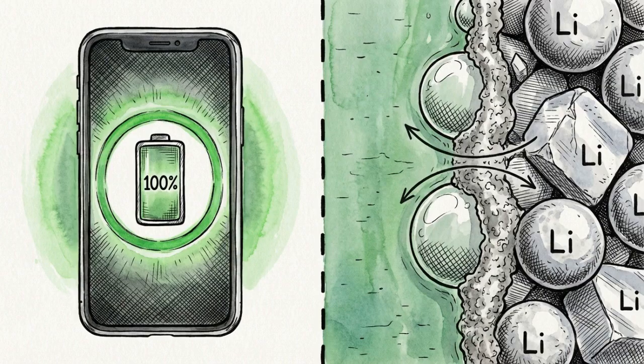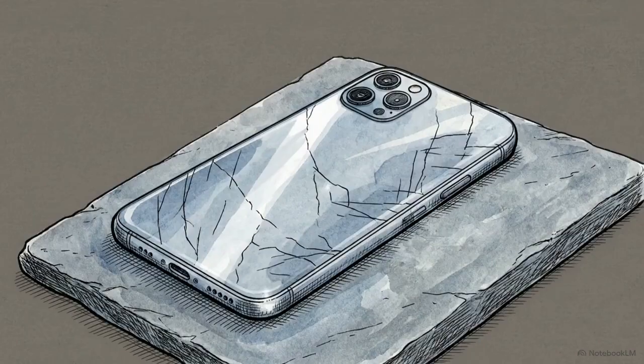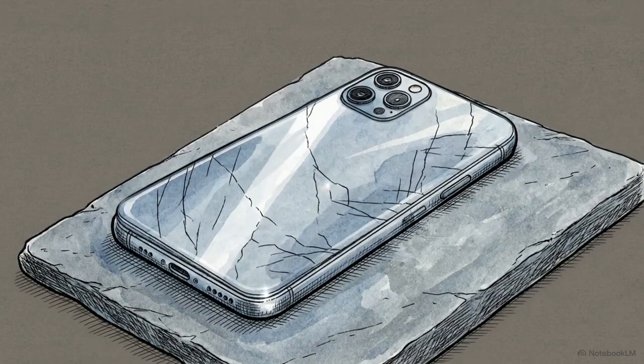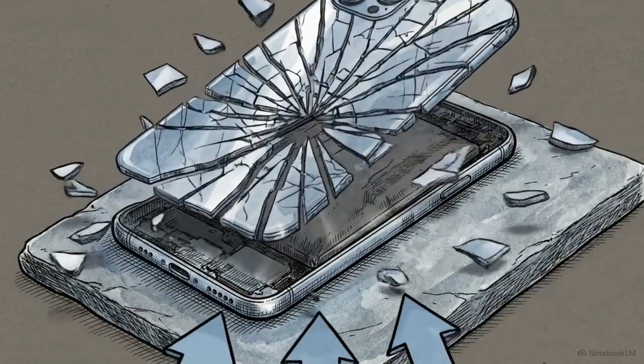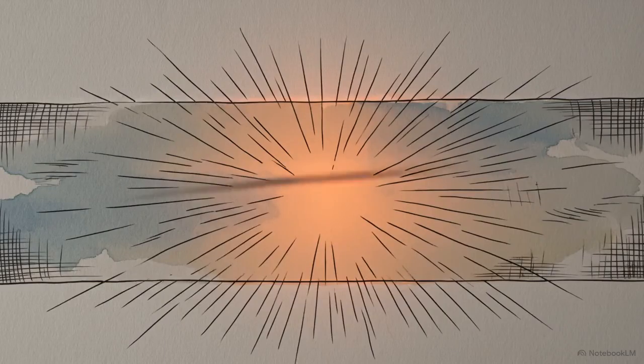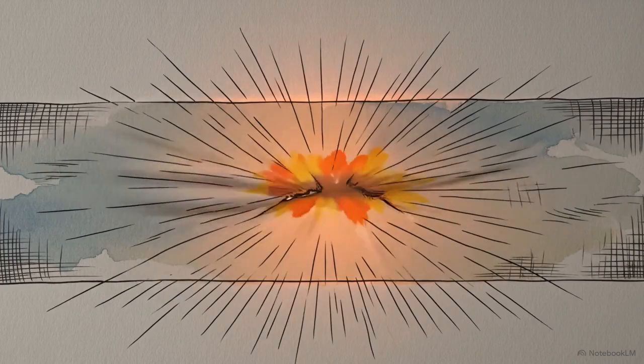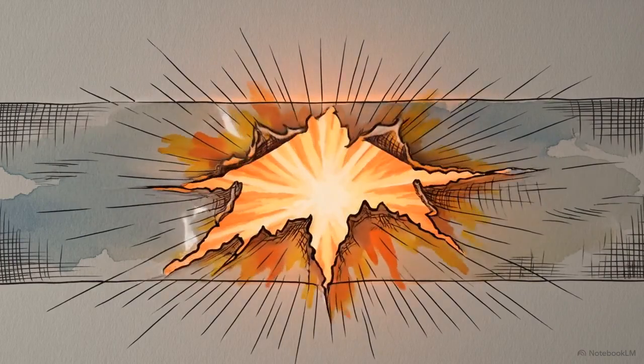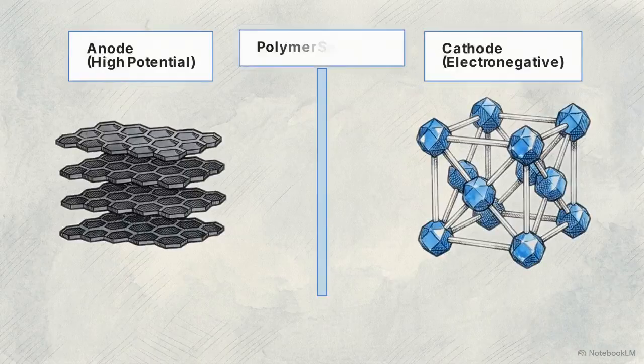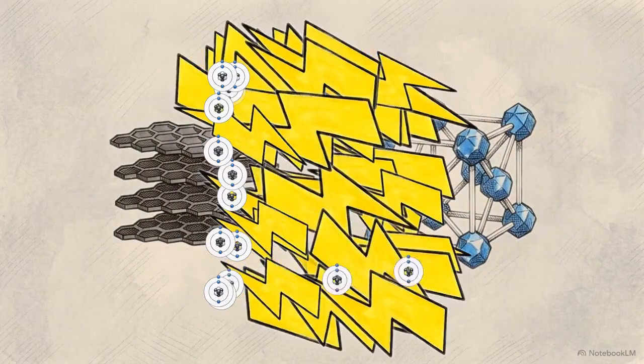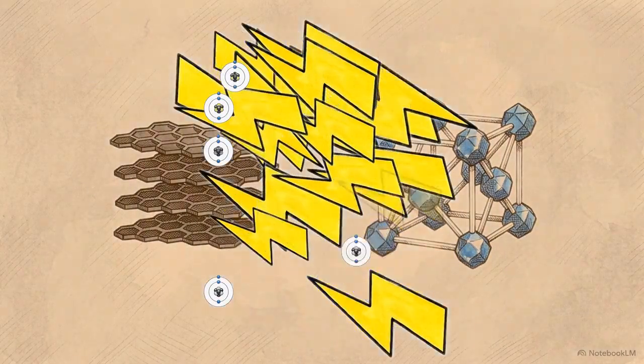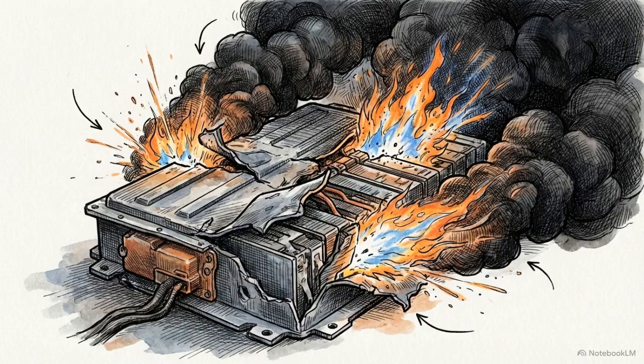Maintaining a 100% charge also degrades the cell through parasitic reactions, where lithium reacts directly with the electrolyte solution. While chemical degradation reduces the runtime of the battery, mechanical failure leads to the destruction of the device. The final component is the separator, a synthetic polymer barrier that prevents the anode and cathode from making physical contact. If this separator fails, the high-potential anode and cathode mix directly, bypassing the external circuit. This results in thermal runaway, an uncontrollable, self-sustaining chemical fire that causes the battery to explode.